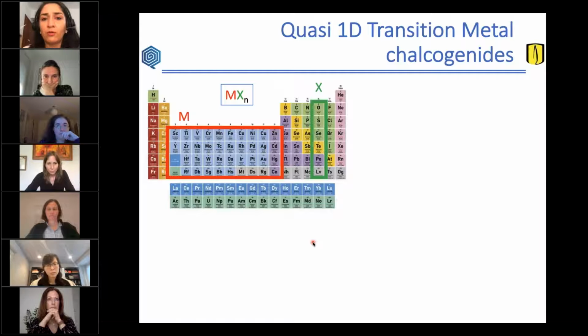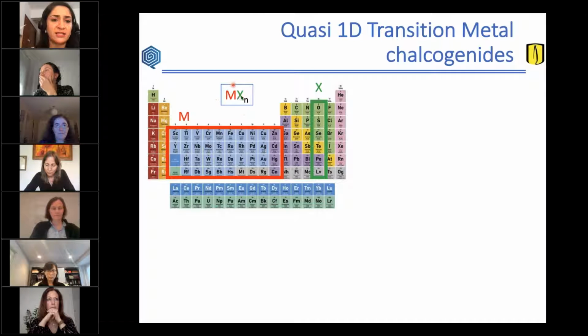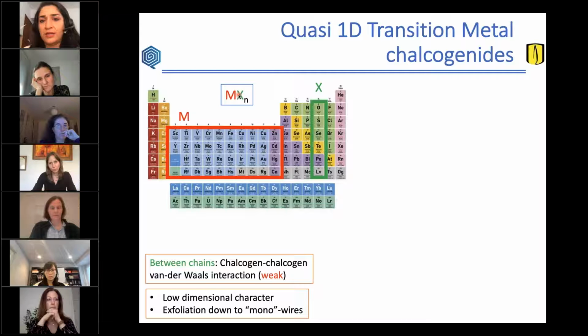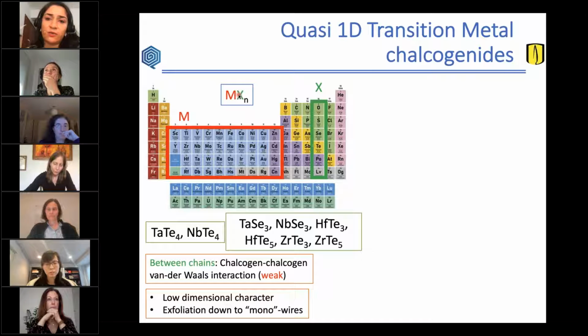So the first example I want to show you is the one for the quasi-1D transition metal chalcogenides, which have the general form of transition metal atoms, in the center of this periodic table, and a certain number of chalcogen atoms. And depending on the number of these chalcogen atoms, we can have two-dimensional materials or quasi-one-dimensional materials. So this low dimensionality comes from the van der Waals interactions among different layers or chains in these compounds, given that we have strong bonds among certain atoms, and weak van der Waals interaction among others, among the chalcogens. So examples of these quasi-1D transition metal chalcogenides are the family of the tetrachalcogenides, the TaTe4 and NbTe4, that I'm going to be talking about.